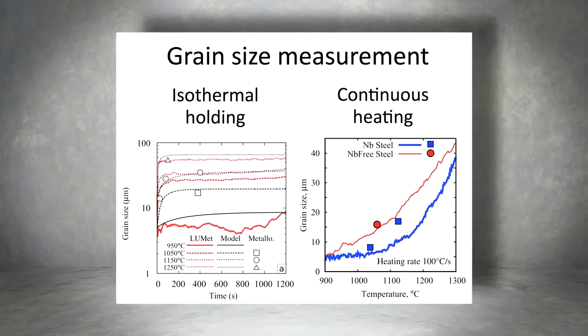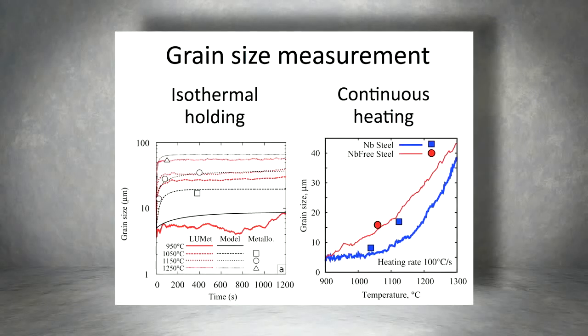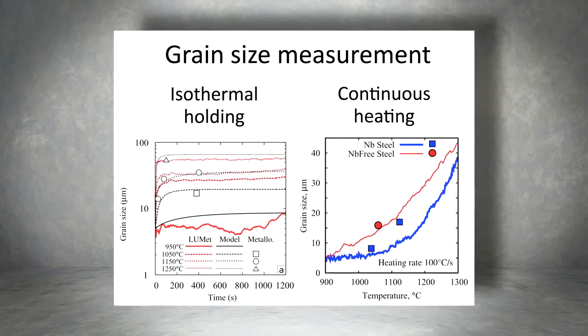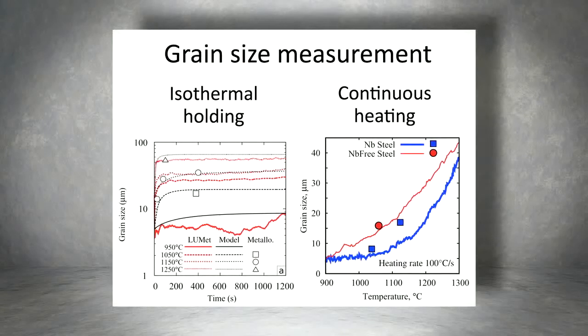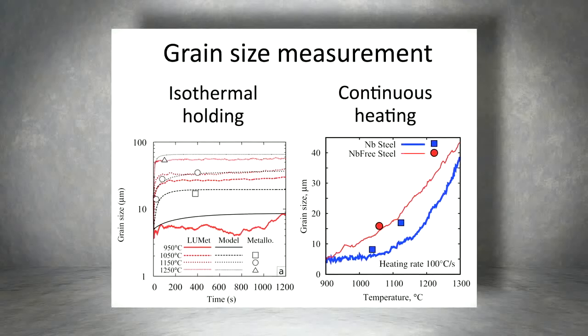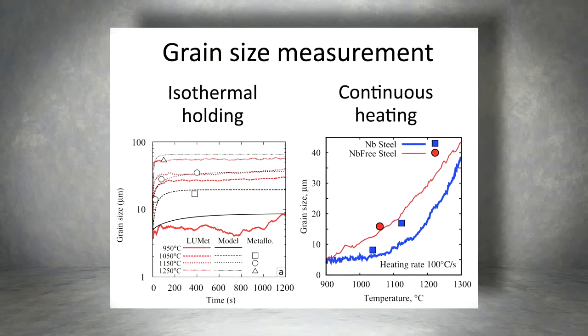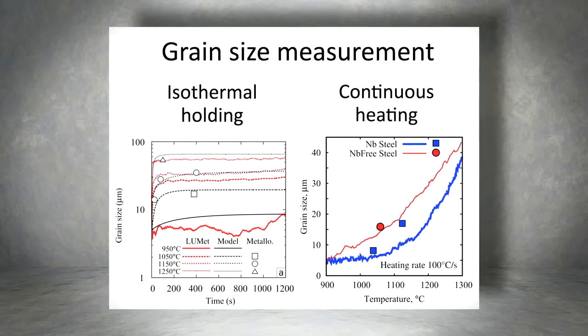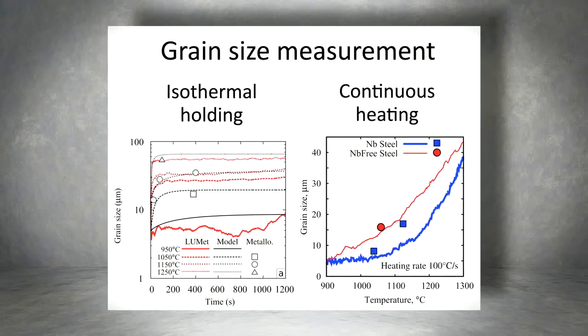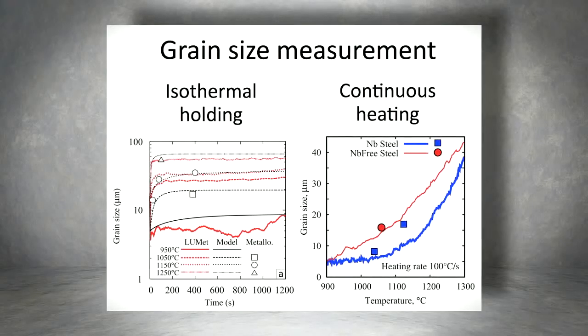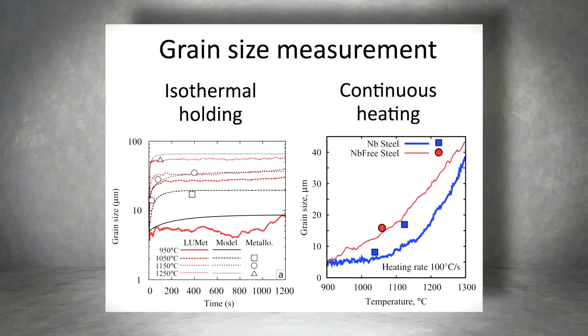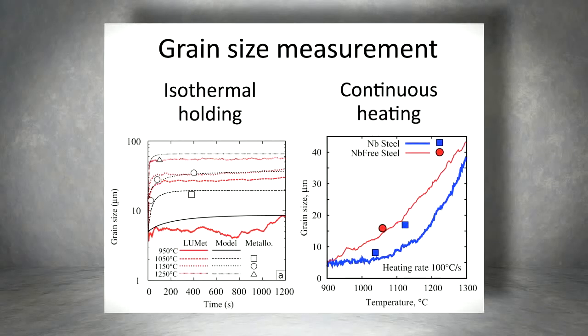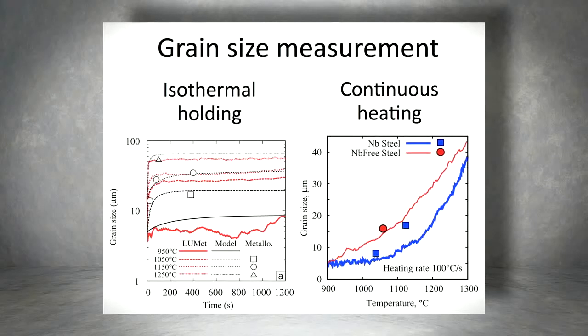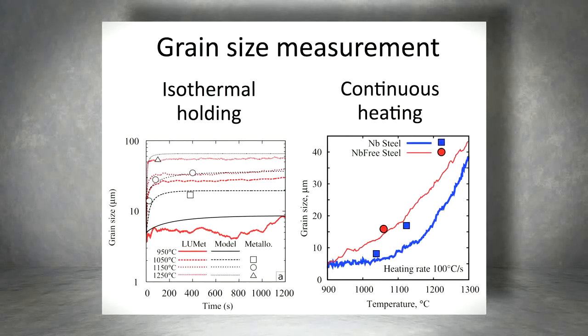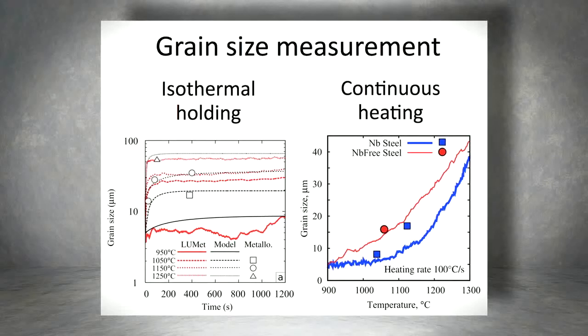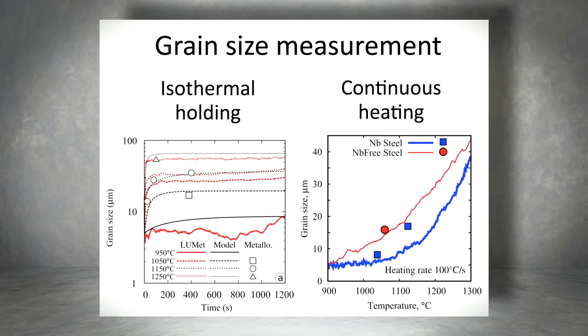So let's look at an example. One of the breakthroughs of this system was really to measure the austenite grain size in steel, because in steel this austenite phase is only stable in the very high temperature domain, and as you cool down the alloy, this austenite phase transforms into other transformation products, and it's impossible to measure this grain size. However, the size of those austenite grains is very much related to the final mechanical property of the material, and every steel company needs to control this grain size very accurately during what we call the hot rolling process.